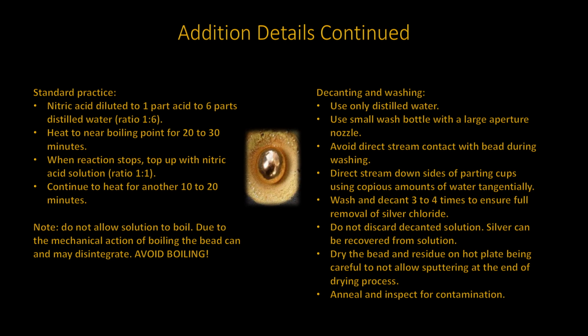When drying on the hot plate, do so with a lower temperature. You want to ensure that the sputtering of the last drops of liquid does not occur. A slower evaporation will ensure that there will be no losses due to sputtering, as the process of sputtering can and does dislodge the fragments from the bead and can eject them out of the parting cup. Once dried, cooled, and annealed, inspect the beads for contamination as well as the parting cup. Any silver left on the bead will show up as dark spots or a stain on the parting cup.